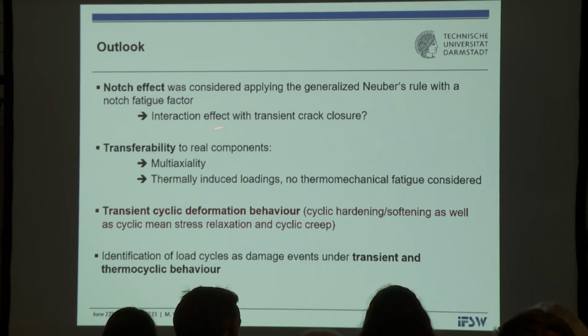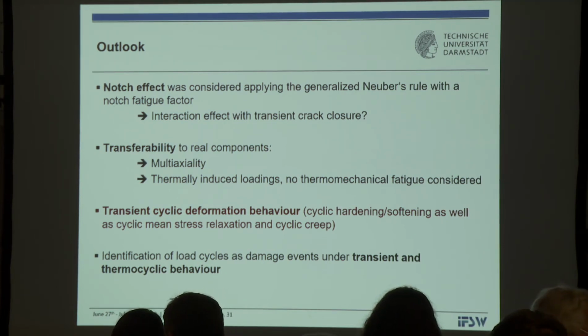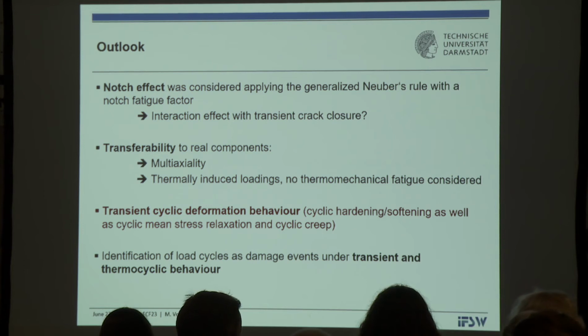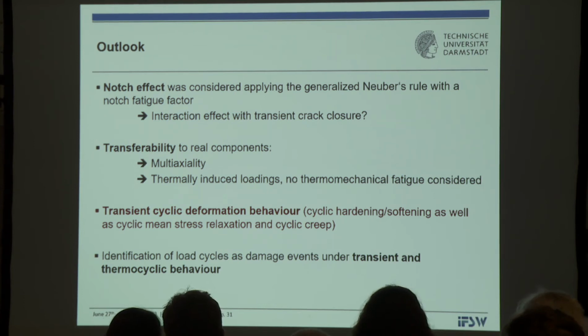The notch effect we considered by simply taking generalized Neuber's rules and a notch fatigue factor. We did not deal with multiaxiality or thermomechanical loads. We did not cope with the problem of transient thermocyclic behavior. And what was astonishing for me is that if we want to arrive at highly accurate life prediction results, we have to use plasticity models which are able to take into account cyclic hardening, cyclic softening, mean stress relaxation, and this and that. It's not the case that we couldn't do that. We could, but it takes a lot of effort to include that in following up research work.